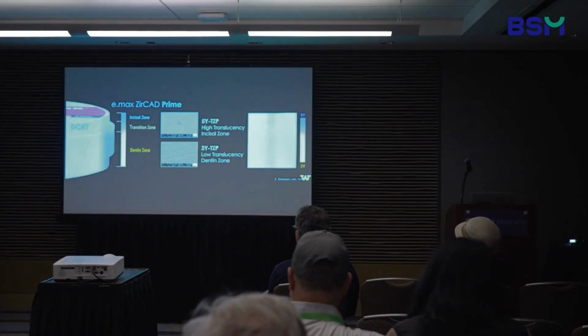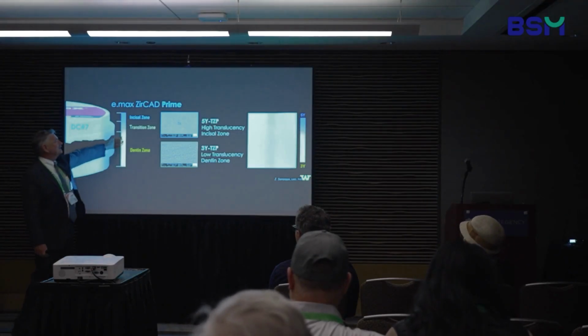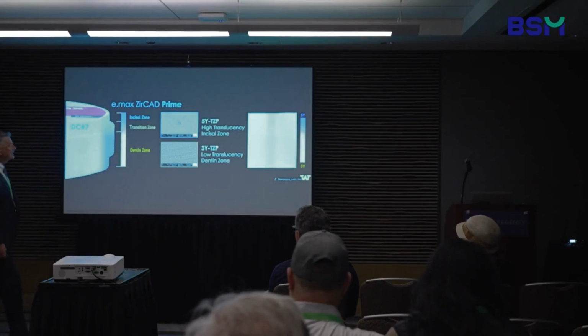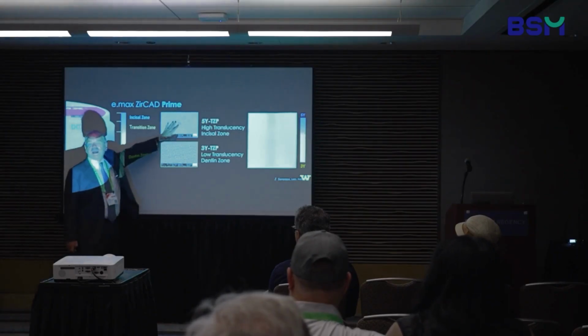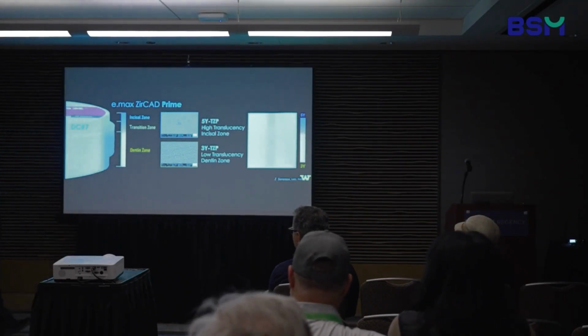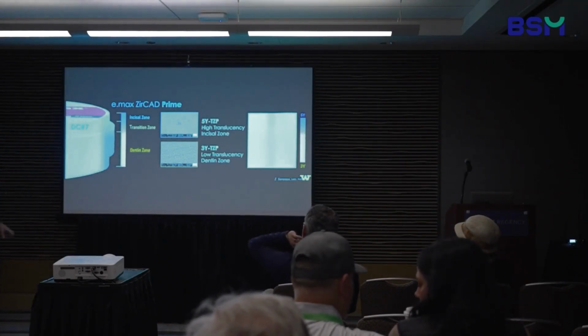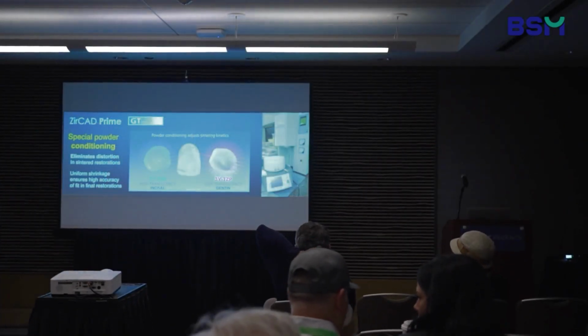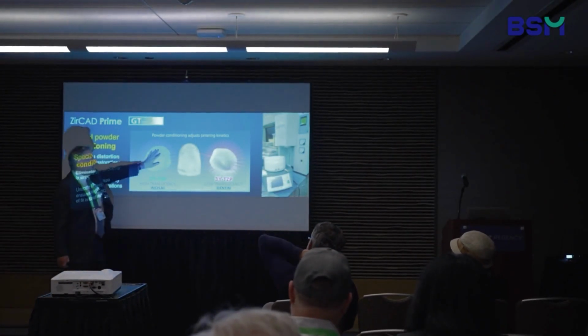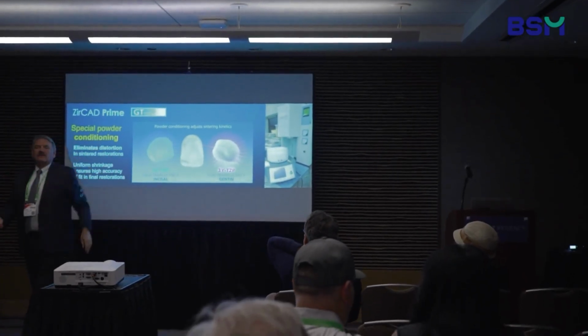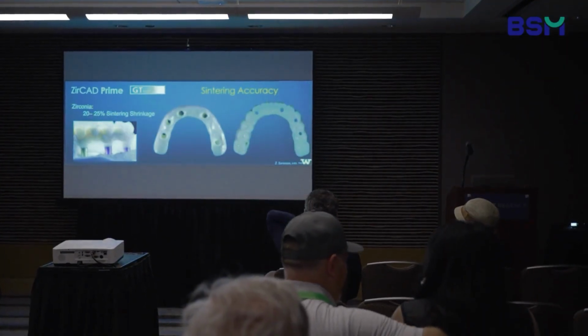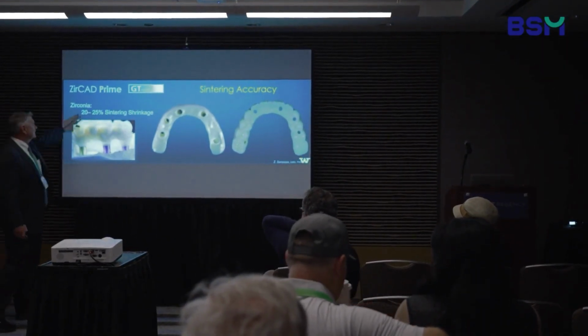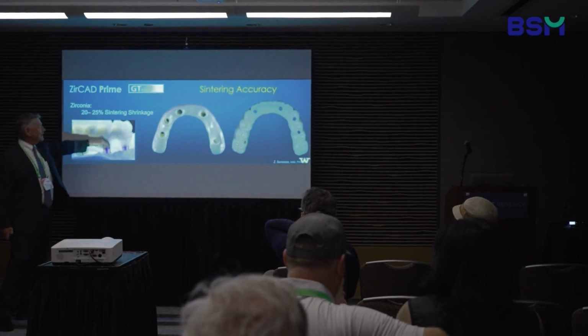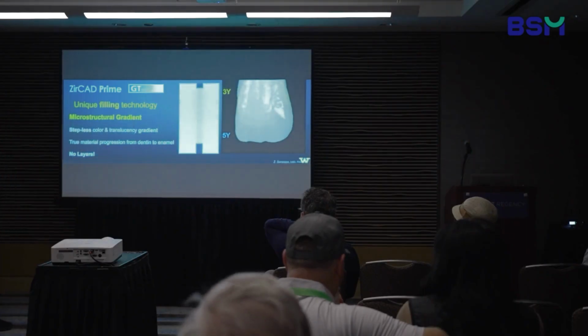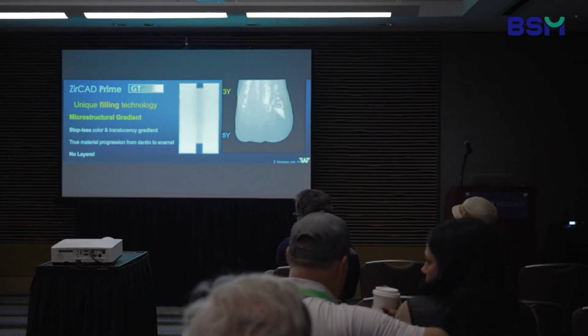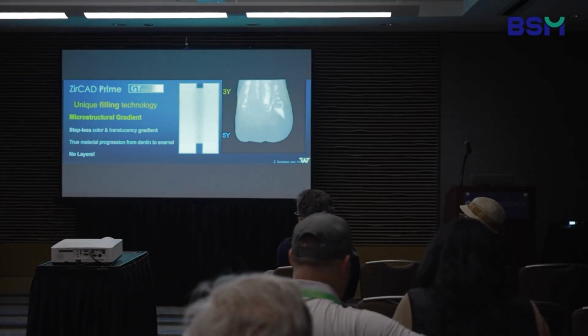And then probably the most exciting material we have now is the Zircad Prime material, which goes from 3Y to 5Y, which is really kind of the ultimate material, especially if you want to do bridges. Pretty amazing. They were able to add things to each of these and get them within the same coefficient of thermal expansion. Again, it's crazy to me how we have that 20-25% shrinkage and you can still get it to fit onto our teeth or onto our implant abutments.